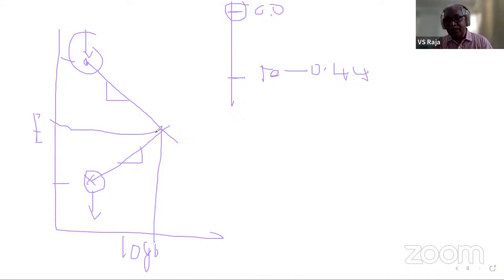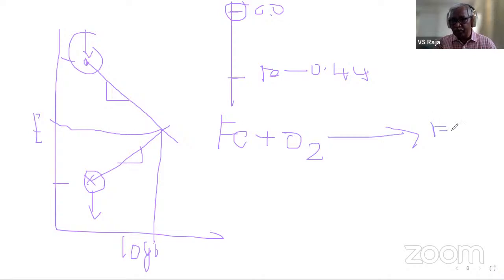The gaseous oxygen directly interacts with the metal, right? Because of high temperature, iron will directly interact with the oxygen, and it can form a series of oxides. It can form FeO, Fe2O3, Fe3O4, depending on the temperature and the partial pressure of oxygen. Now, the protecting capacity of this oxide is very important. Some oxides are highly conducting. They can conduct ions, they can conduct electrons. If the oxide is highly insulating, it becomes more protective. So we talk about p-type semiconductors, n-type semiconductors, and which ions are moving. So understanding the conducting behavior of the oxides is very important to see their protecting capacity.